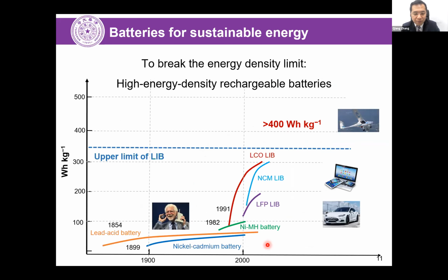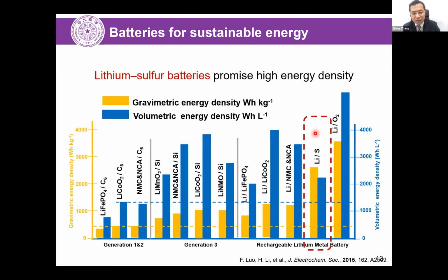If we track the history of the battery, it is found that the energy density increase is rather slow. If we check the lead acid battery or nickel cadmium battery, the energy density rises quite slowly. With the emergence of the lithium-ion battery, based on lithium chemistry, it is rising quickly. However, if the battery is based on carbon anodes, the energy density was always below 350. Well, if we try to develop applications like unmanned vehicles or other requests which require batteries with very high energy density, it is found that new emerging energy chemistry was requested.